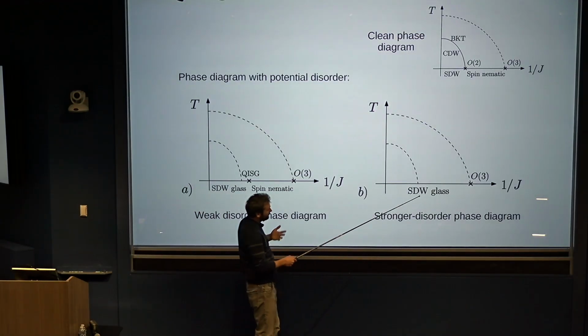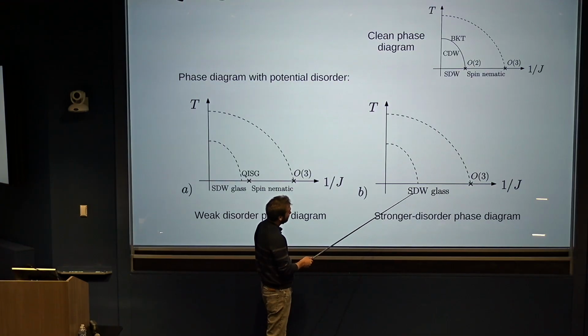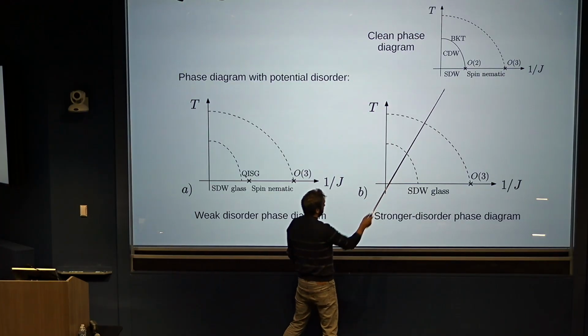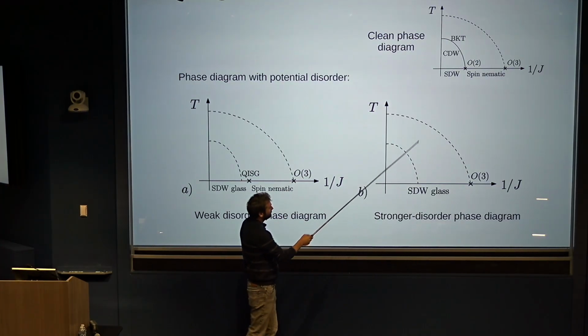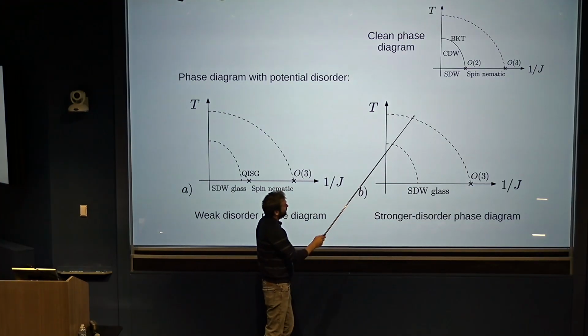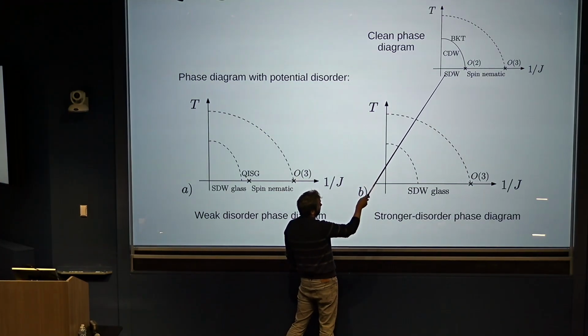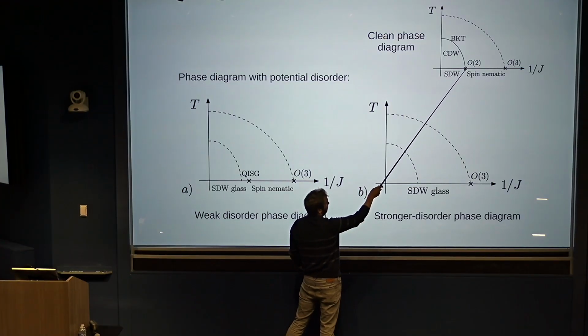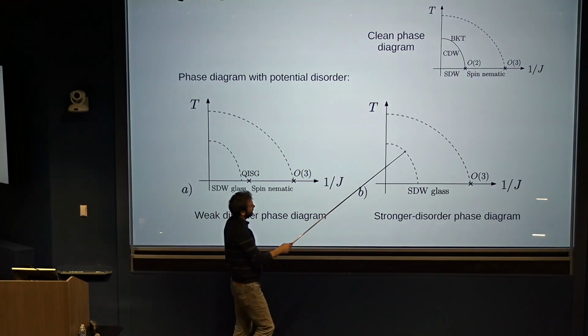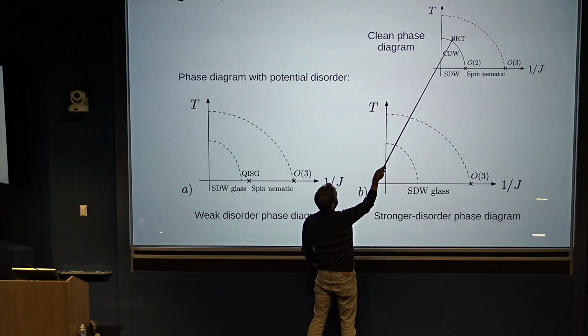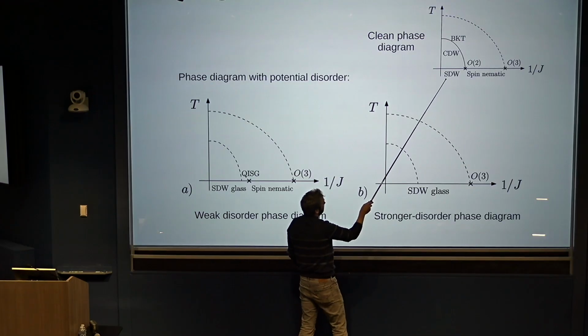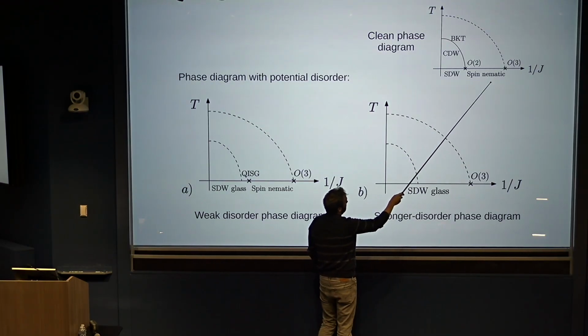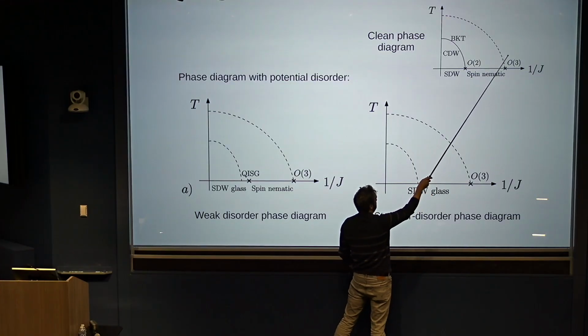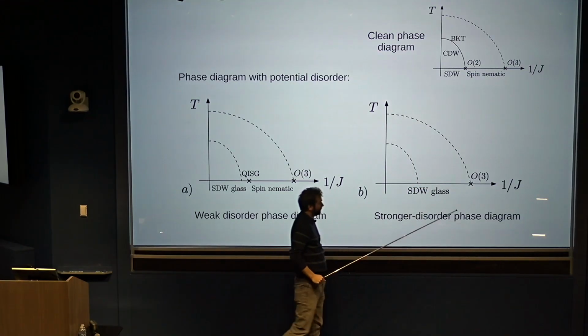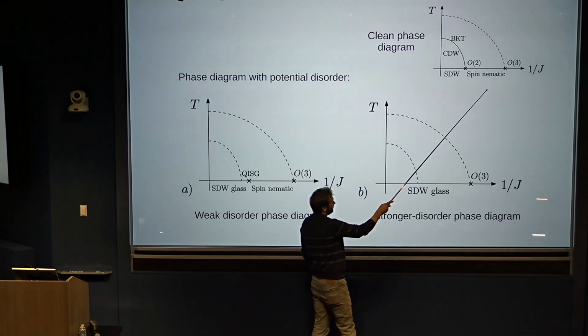Right. And so this is basically all that remains when you add potential disorder to the system. So the spin nematic becomes a spin density wave glass. It turns out the spin stripe also becomes the same phase of matter. There's no phase transition here anymore. Also, Imry-Ma tells us that the charge order here also disappears. This is why there's no phase transition anymore. So this phase transition goes away, then the BKT goes away. These are now all crossover regions, and this all becomes the spin density wave glass. And there's a single quantum phase transition that remains, which is this O3 transition. But this is now an O3 transition in a completely different universality class than this transition.